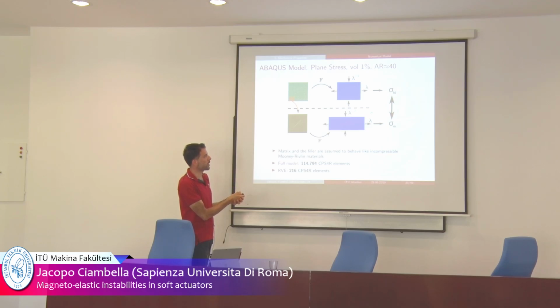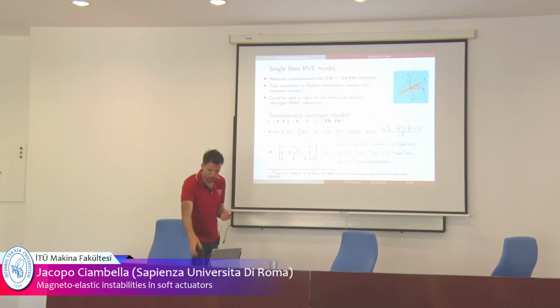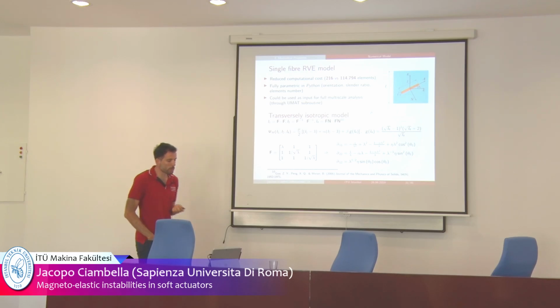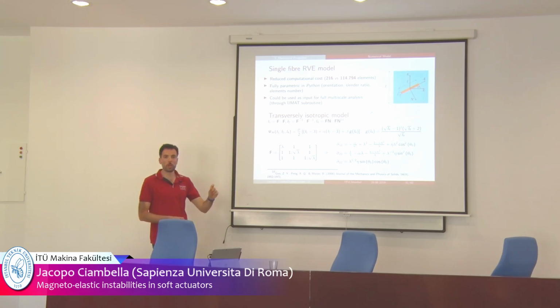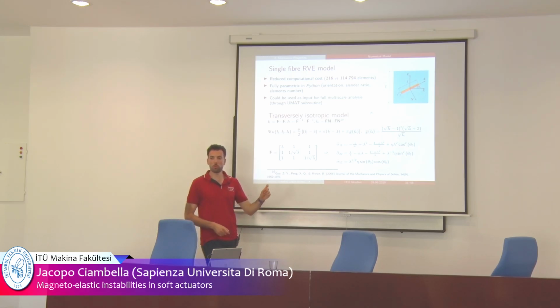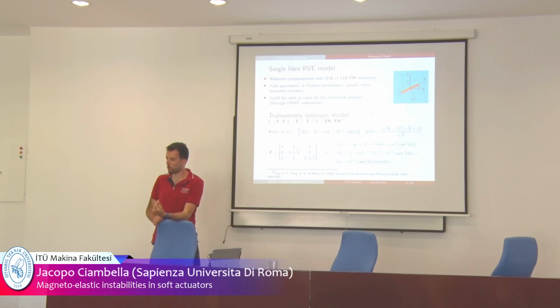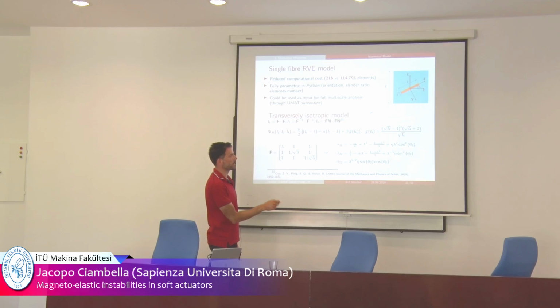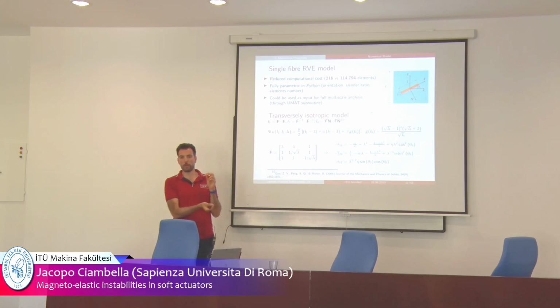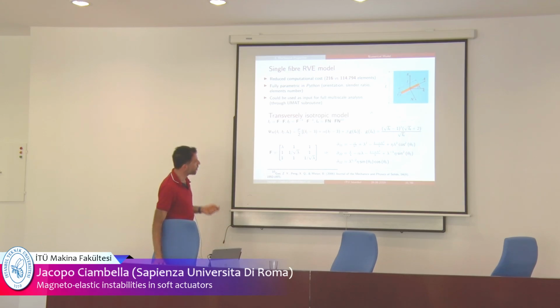But to check if this model is good for this type of composite, we also ran simulations on this level, and we compare the two stresses. This was the idea. We wanted to do the single fiber model because, first of all, it has a reduced computational cost compared to the entire specimen with the fibers. You can use this for purely multi-scale problems. In a multi-scale problem, at each element, at each material point, you have to solve a microscopic problem, which is exactly that one. So we used a Python routine to make the microscopic level and the macroscopic level communicate in Abaqus.